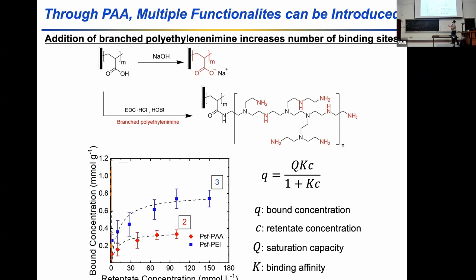There are two parameters that define the Langmuir isotherm. Capital Q is the saturation capacity: what's the most amount of material, in this case copper ions, I could put on the surface at saturation? And K is the affinity, which defines what sort of solution I'm able to treat. Higher affinities mean I'm able to remove ions from even lower concentration solutions. We have the Langmuir isotherm for the polyacrylic acid functionalized membranes as the red diamonds, and it's got a modest uptake of copper ions at a nominal affinity.